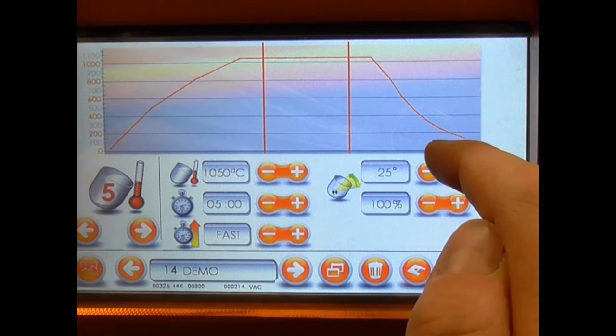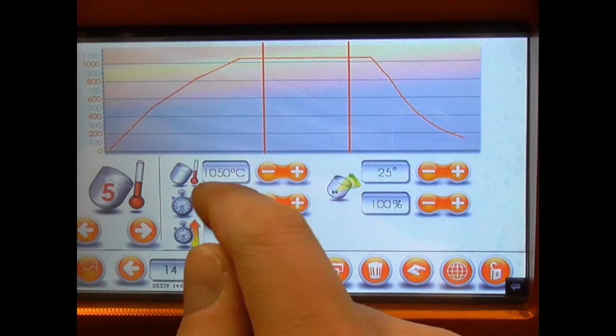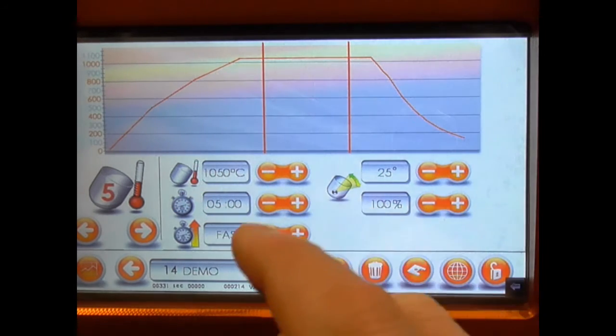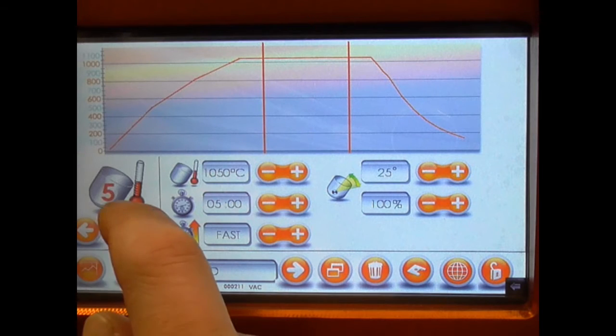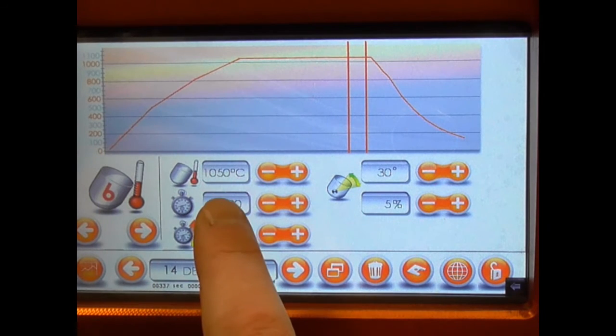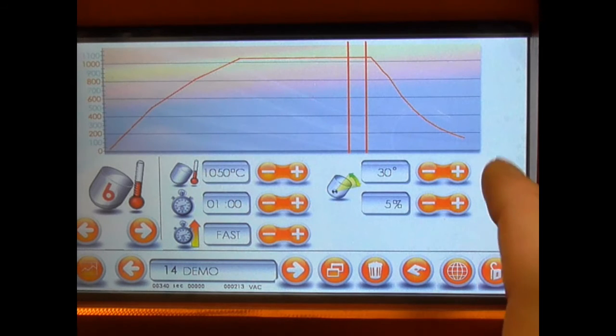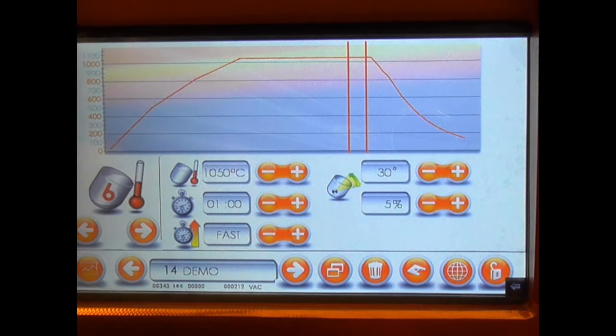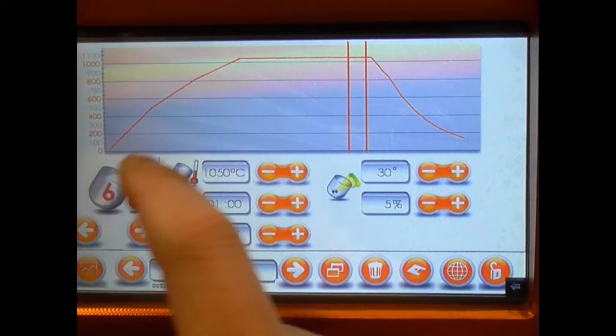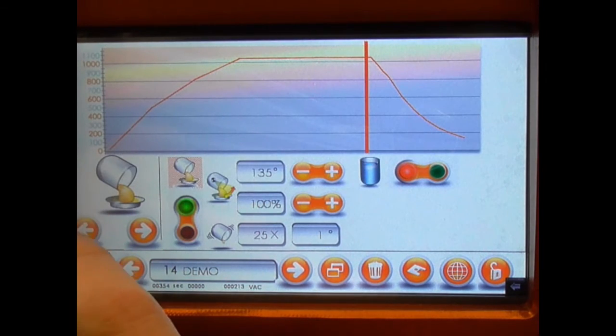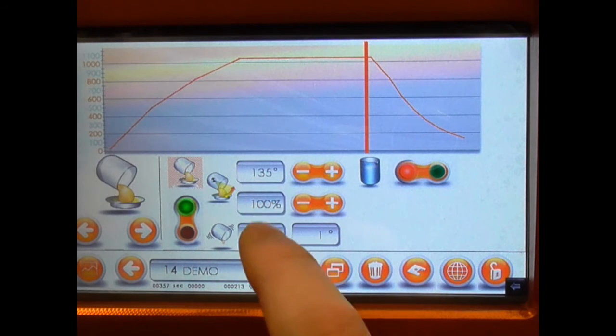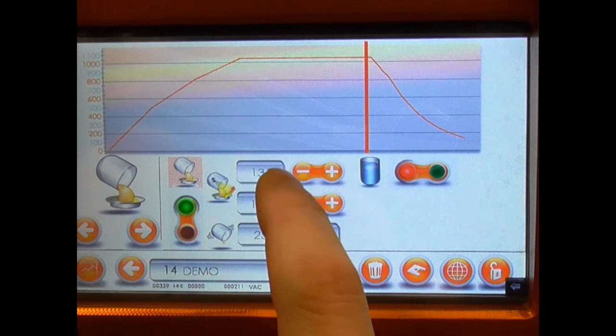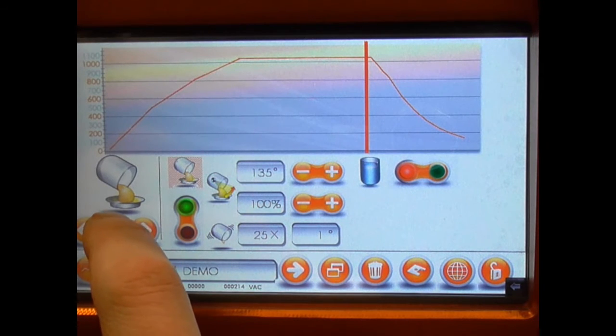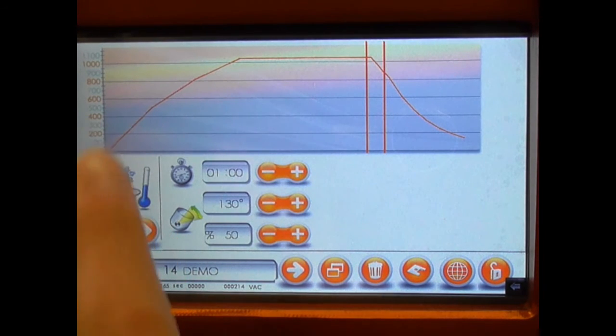At step 5 here, we will start to induce motion to the crucible. So we have the angle here, the speed of agitation, and the duration. So 5 minutes, 25 degrees angle back and forth at 100% speed. The last heating step, we will stay 1 minute and modify the angle of the crucible a little bit. We want here to release bubbles if bubbles are created during the fusion and reach a higher level on the crucible wall, for example. When it's done, it will be the pouring step. We have default values of pouring here related to the pouring speed and the position of the crucible, and finally we will enter the cooling step.